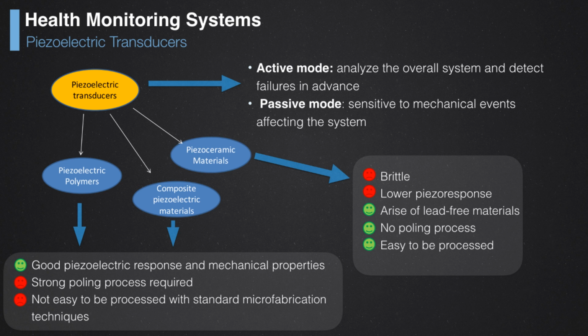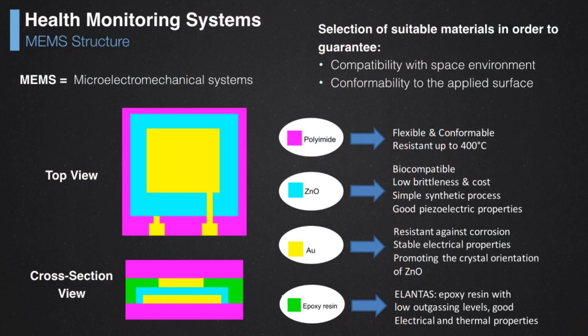Another solution is to work with composite materials, meaning that you have hybrid structures, once again with a polymeric matrix and a ceramic filler, where you may have both the ceramic filler and the polymeric matrix with active properties. So you can select, for example, both piezoelectric materials. So you can use a piezoelectric polymer and a piezoelectric filler. Then you have other problems because it happens, for example, that you have materials with different signs in the piezoelectric constants, and you take the risk to cancel out the effects if the matrix and the filler do not have the same piezoelectric constant sign.